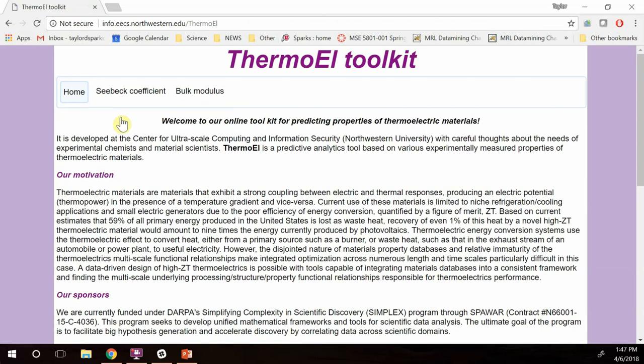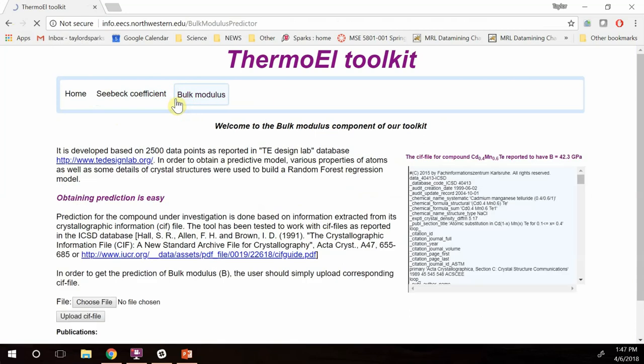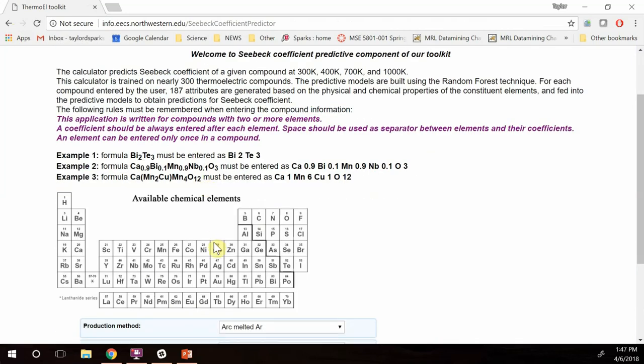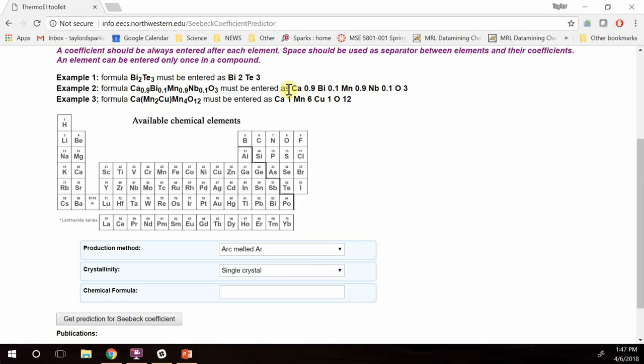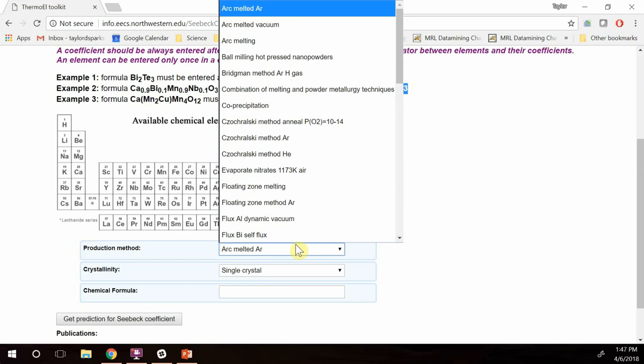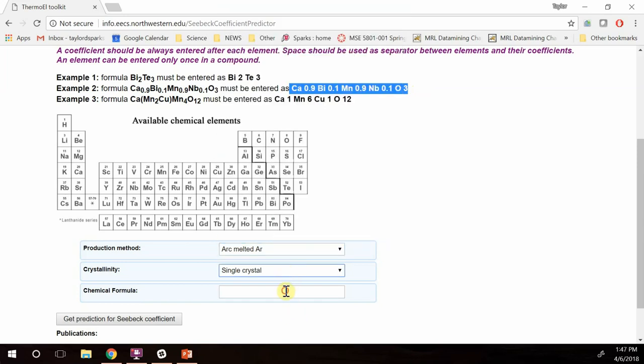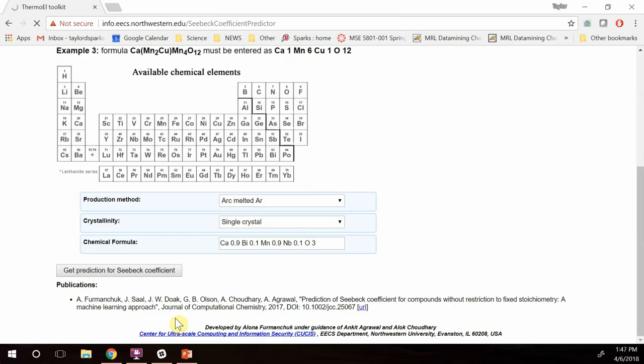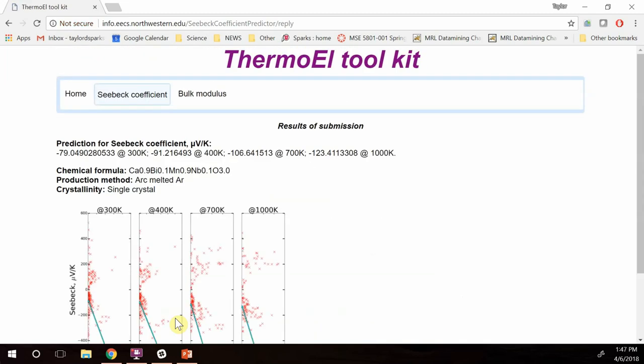Then the thermoelectric toolkit, as I said, has two models, for Seebeck coefficient prediction and bulk modulus. And here you can take things like the production method, the crystallinity, and the formula. Interestingly, we found that it works specifically well for doped compounds. So here you see non-stoichiometric compounds, and it's a temperature-dependent prediction: the Seebeck coefficient at different temperatures.